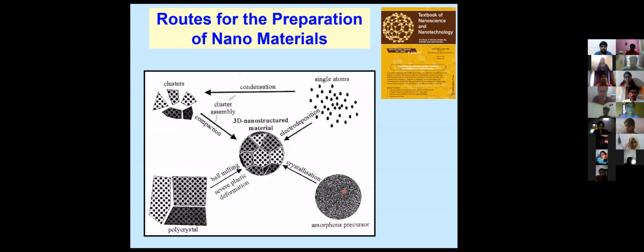People talk about PVD, CVD, physical vapor deposition, chemical vapor deposition, where you can evaporate something and everything is in the form of gas, and the atoms in the gas are allowed to deposit onto a cold substrate and ensure that during the deposition, you do not allow these deposited particles to grow to bigger size, and you get nanoparticles. So there are so many such ways, which are all called bottom-up approach, where you are starting from atoms and